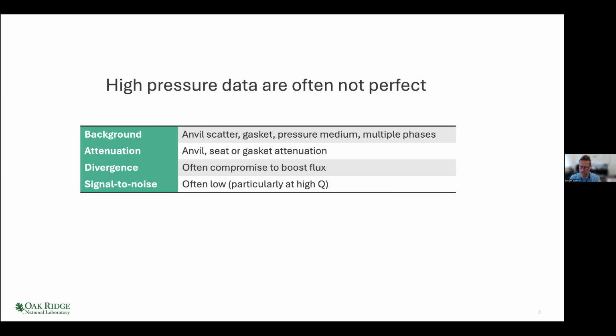That's cleaner if you're using a monochromatic beam. If you're using a time of flight beam, as I'll touch on later, it actually can become very complex and non-trivial. We typically suffer from higher divergence as well because we're exchanging degraded divergence for a higher flux. Our samples are small and we need that intensity. And usually our signal to noise is poor, especially at high Q.